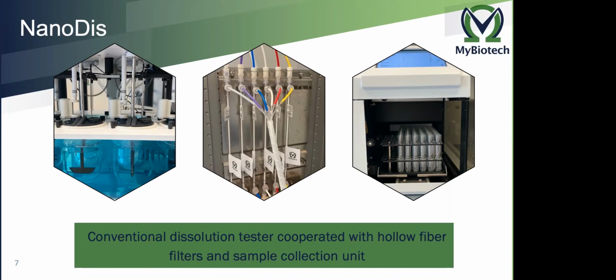Our idea was what happens after we take the sample from this apparatus, how we can separate the nanoparticles from the sample in a very quick way. For that, we decided to use cross-flow filtration modules. The good thing about cross-flow filtration modules is they come with different membrane pore sizes, so that I can adjust them according to the nanoparticles.